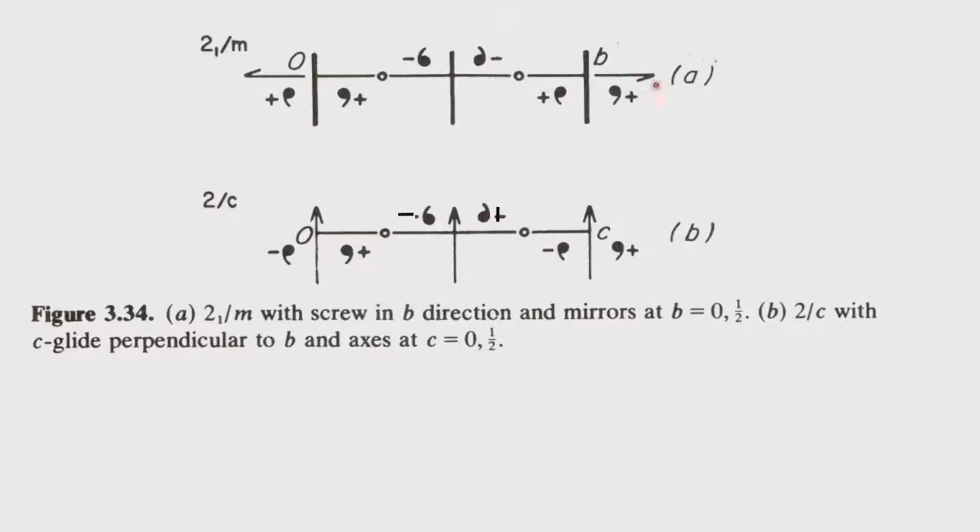Now, these two observations have to be incorporated when we now discuss the space groups which involve non-translational periodicity associated with them. Space group like P 2 by m, space group like P 2 by C, space group C 2 by m, which is also C 2 1 by m, as we have seen C 2 1 and C 2 are one and the same. Then of course, C 2 by C. We will also have the combinations of both these having translational symmetry, because a point group 2 1 by m can generate a centrosymmetric space group 2 1 by C. So, we can have two additional space groups P 2 1 upon C and also C 2 upon C.